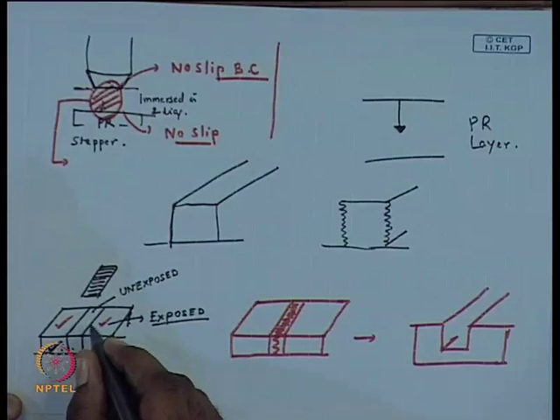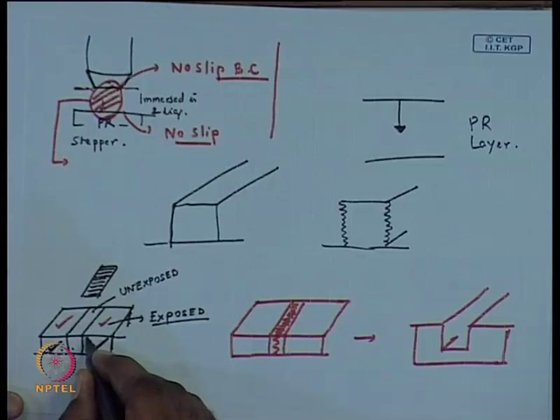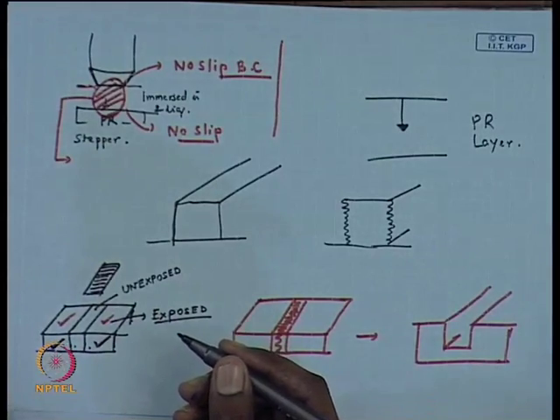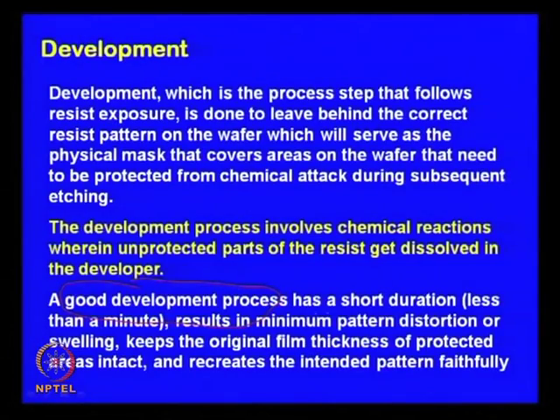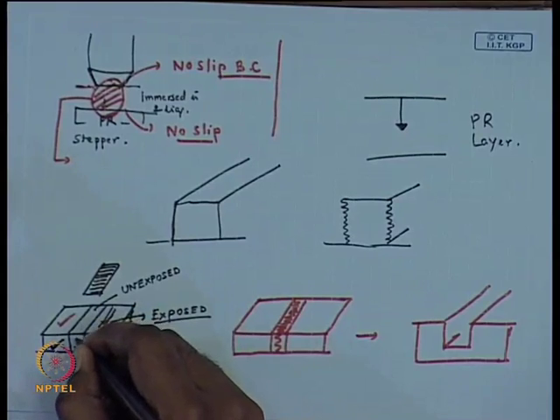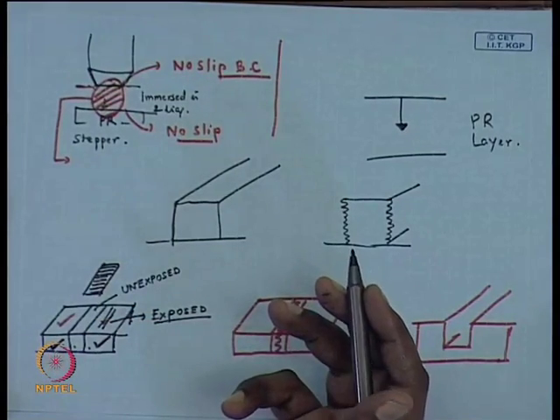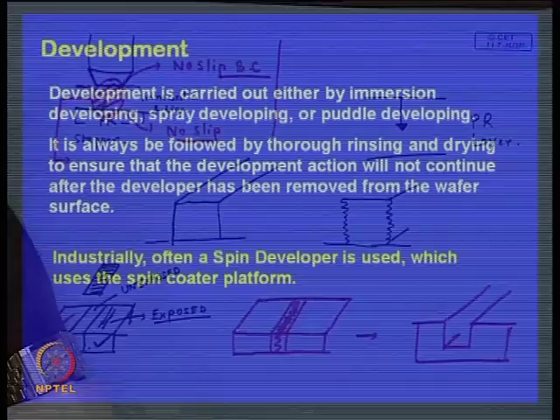So, if you use the developer for a very long period of time, what is going to happen is that alongside dissolving these areas, it will also affect this structure. So, that will affect the structural fidelity. This is important: a good development process has a short duration, results in minimum pattern distortion or swelling, keeps the original film thickness of the protected areas intact, and retains the intended pattern faithfully. So, it removes only this, it does not affect the thickness of this layer, and it does not lead to any distortion of the pattern.